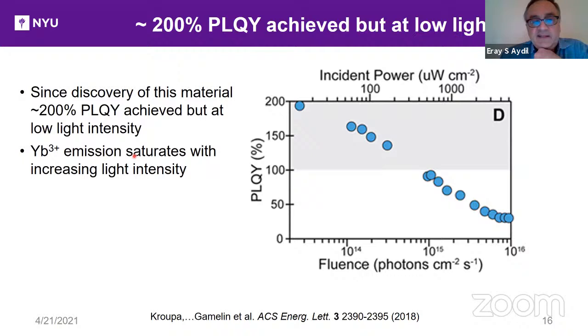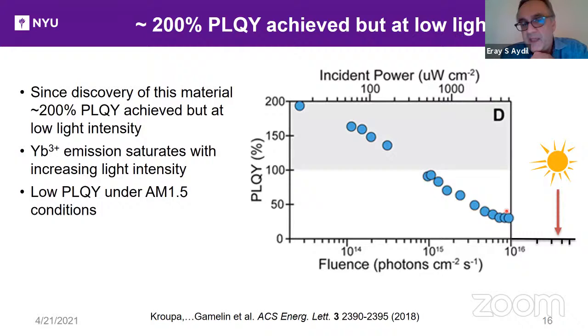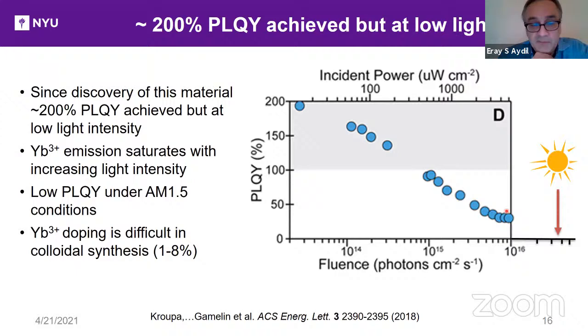One issue is that ytterbium emission saturates with increasing light intensity. So you get 200% at low fluence and it decreases slowly. And that is problematic because here is the sun intensity. So there's low PLQY under AM 1.5 conditions. So that's one problem. Putting in enough ytterbium doping is difficult, particularly in colloidal synthesis. And ytterbium has a 3+ valency, whereas in cesium lead chloride, lead is 2+. So it doesn't like to go in as much. Although the fact that it is a defect may help the quantum cutting. At least that's one of the hypotheses. But in any case, this problem has to be solved if materials like this should be commercialized.